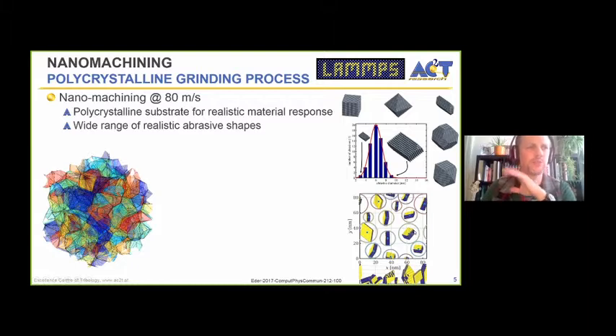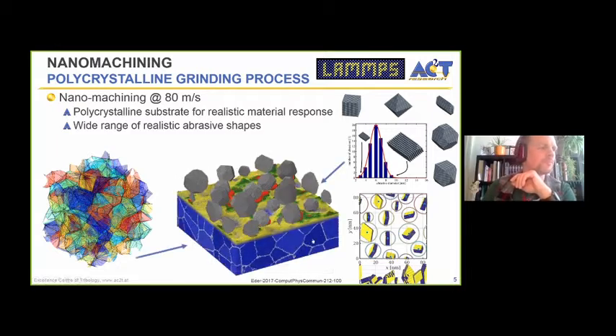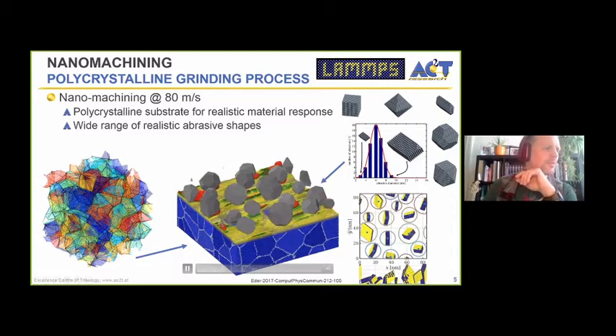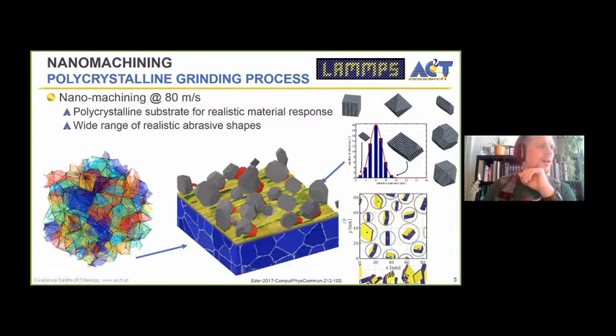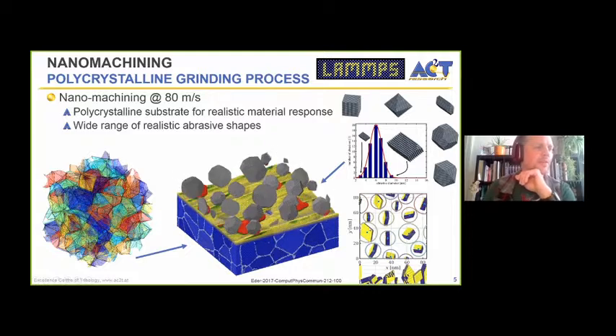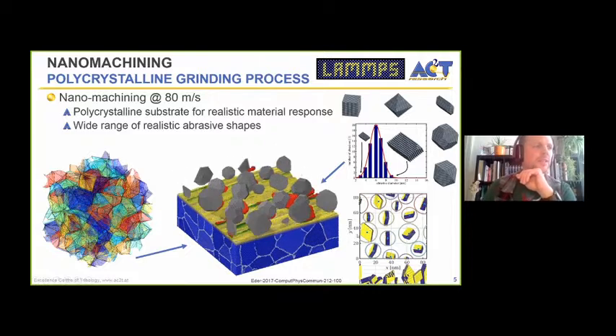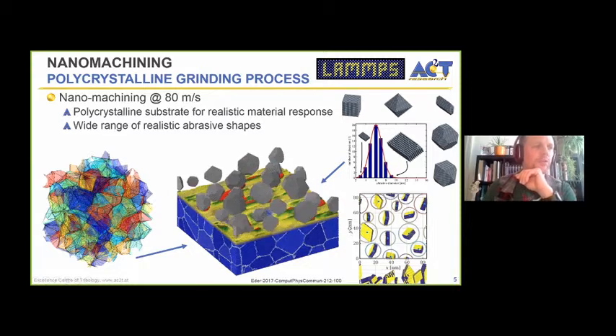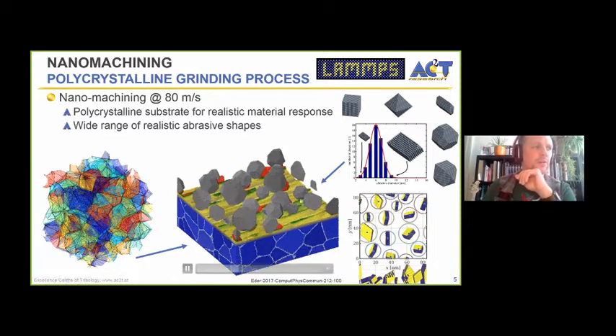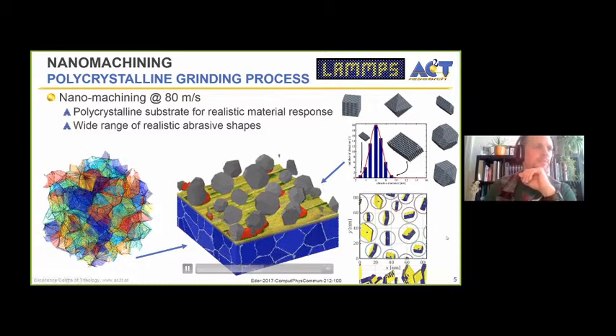You'll see here how I distribute them over the surface, make sure they don't overlap, and so on. Then I shake hard. I make sure that they are jumbled and meet the work piece at random orientations, random rake angles, and then I start grinding away. So this would be about 2 to 3 years old. What this would look like, this is the 60 by 60 by 30 nanocrystalline system. So this would be grinding nanocrystalline iron with cubo-octahedral abrasives.